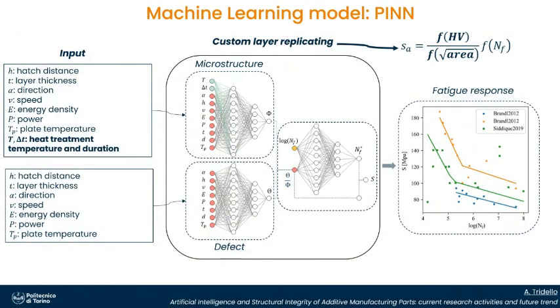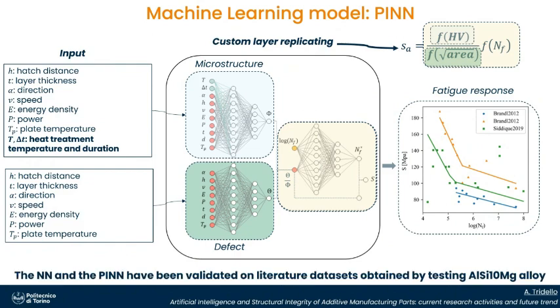This is the scheme that we use. The inputs are the process parameters, and we have a first neural network which starts from the process parameters and the treatment characteristics to predict the influence of the microstructure. Then we have the second one, which predicts the influence of defects. In this case, we don't consider the treatment, since the defects are not so much influenced by treatments. And the last one concatenates these two inputs and, with the number of cycles, can predict the fatigue life. Okay, you can see the fatigue response.